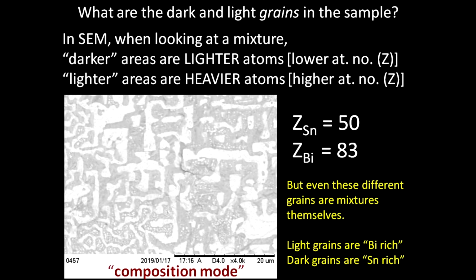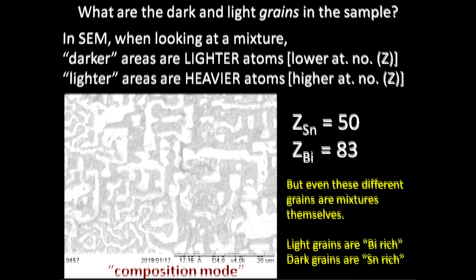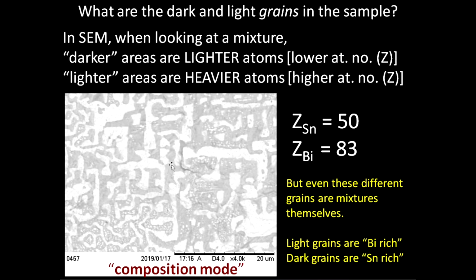This alloy is composed of tin and bismuth, and if you take a look at their atomic numbers over here on the right, we can see that tin, with an atomic number of 50, is much lighter than bismuth, which is atomic number 83. So from that, we can make a prediction that the dark regions are going to be the lighter atoms. And so we should think about this when we look at the remaining pictures. The dark areas should be rich in tin, and the lighter areas should have more bismuth in them.